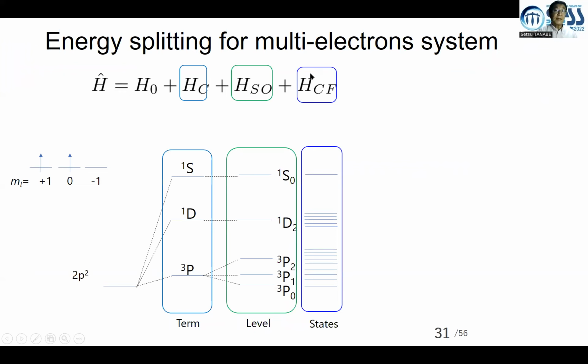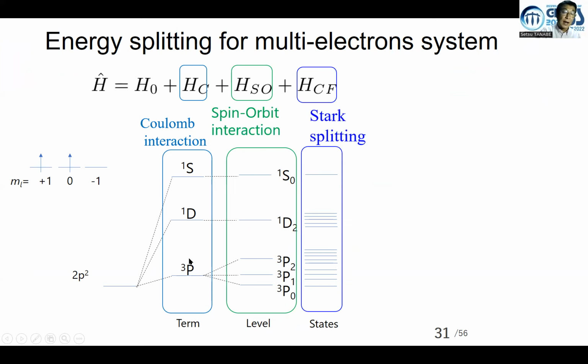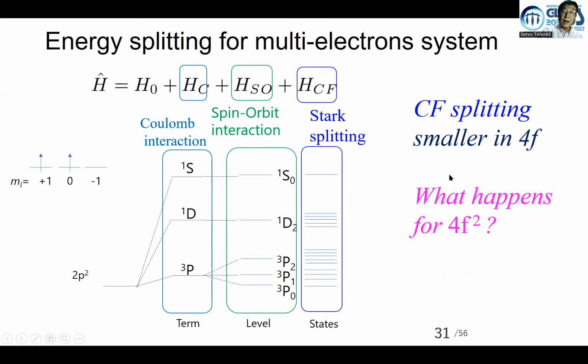And energy splitting for a multi-electron system can be understood like this. First, Coulomb interaction splits most largely, and spin-orbit interaction splits the triplet state into three different J states. And finally, crystal field splitting gives Stark splitting in the case of lanthanides. So crystal field splitting is smaller for 4f electrons compared with other typical elements.